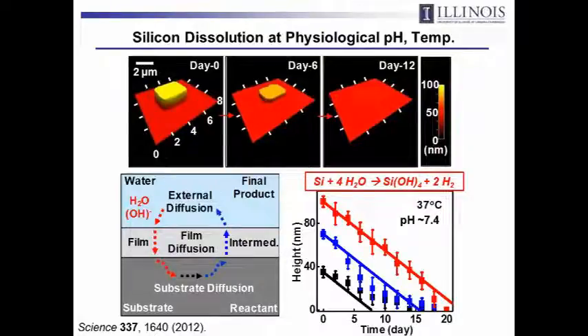in a resorbable format. And what we found is that silicon itself will undergo hydrolysis. It will dissolve at physiological pH in aqueous solution and physiological temperature. The rate is very, very, very slow. So just a few nanometers of silicon will dissolve per day. But if you think about using silicon in very, very thin formats, that might be fast enough for the kind of applications I outlined previously.